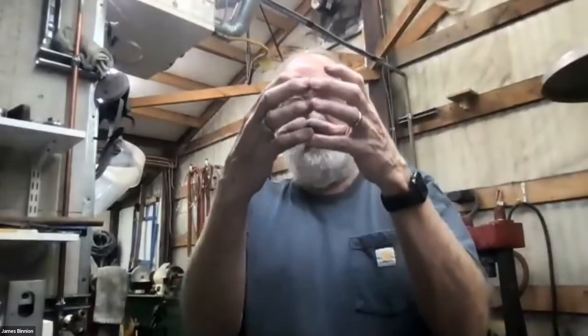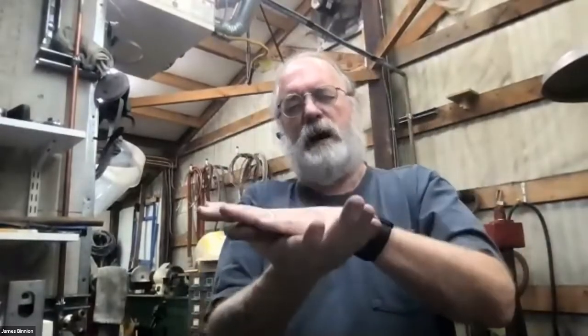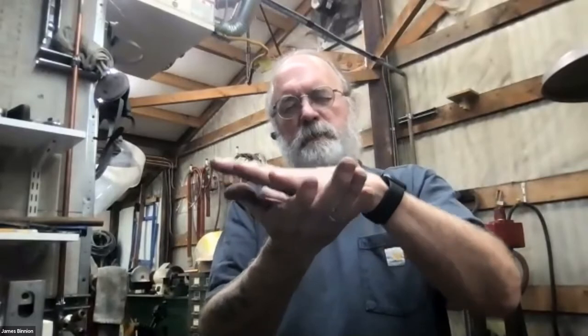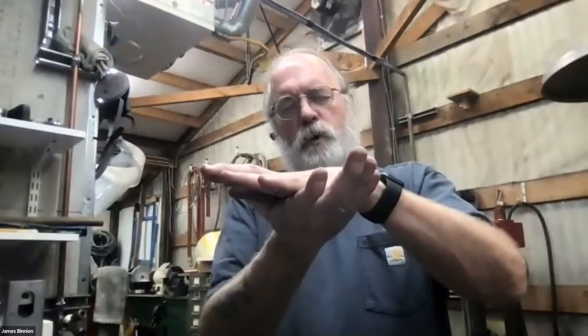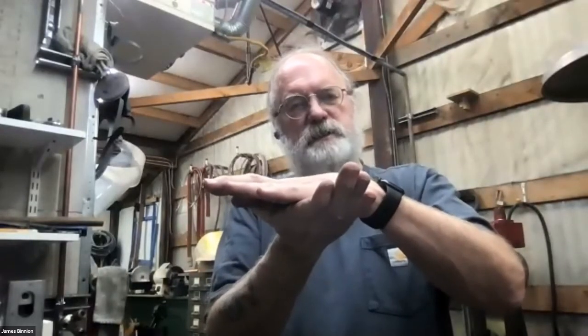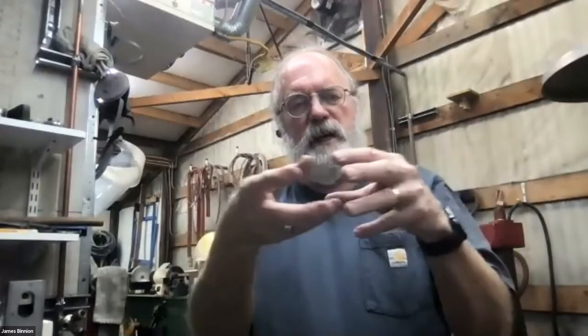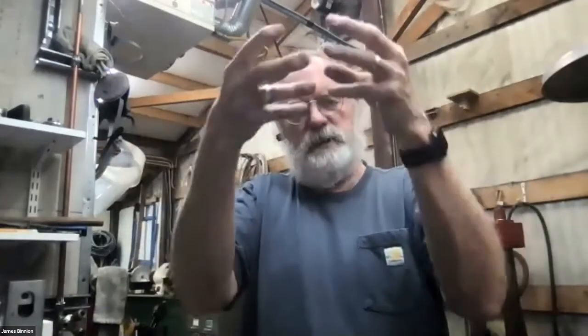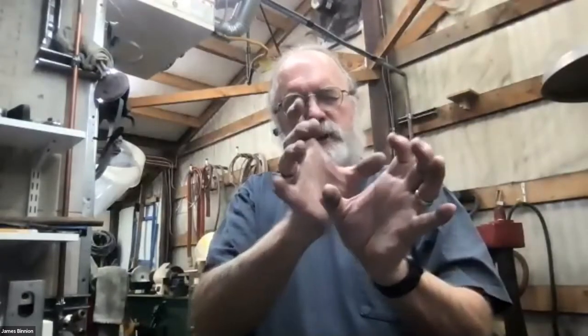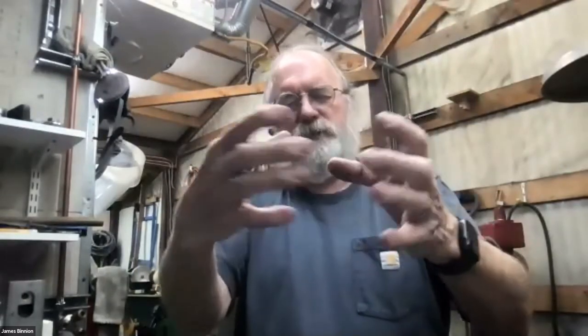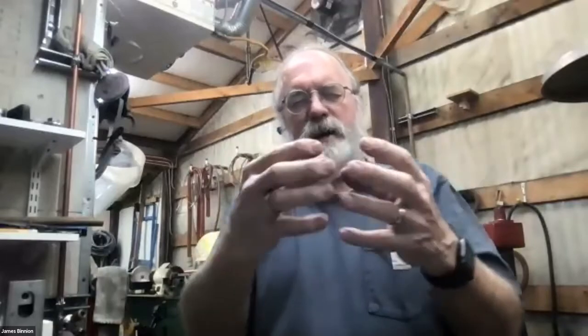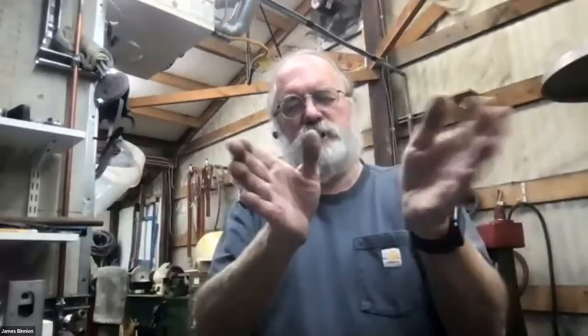You're pressing down with the top and bottom dies on the press. The metal's getting cool where it's in contact with the dies, but the metal in the middle is still quite warm, so it tends to push out and extrude more than the metal that's up near the top and bottom. And that stress, that hoop stress around the perimeter is quite high, and the edges of the material just start to crack.